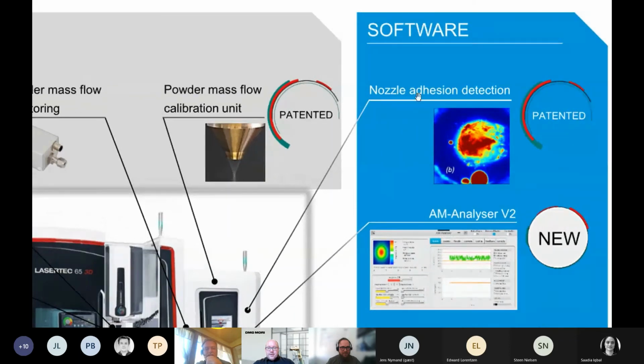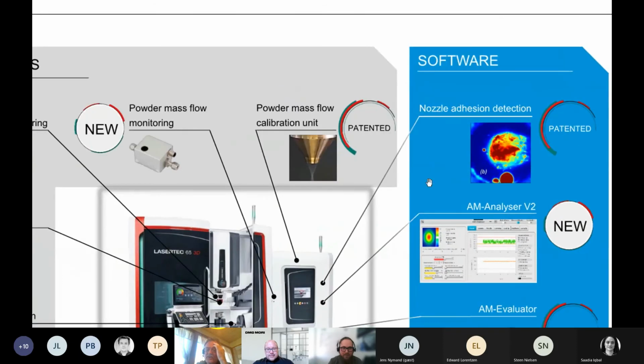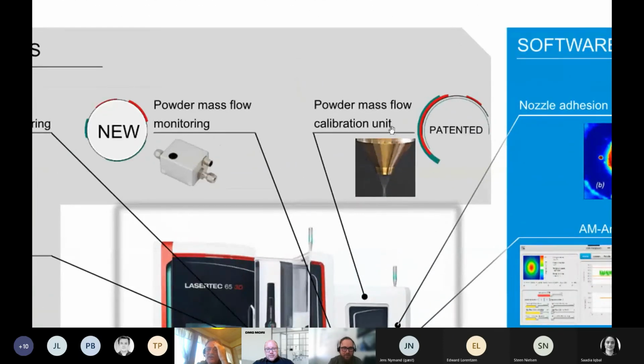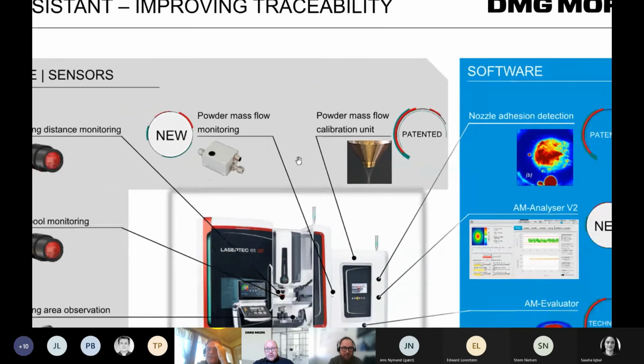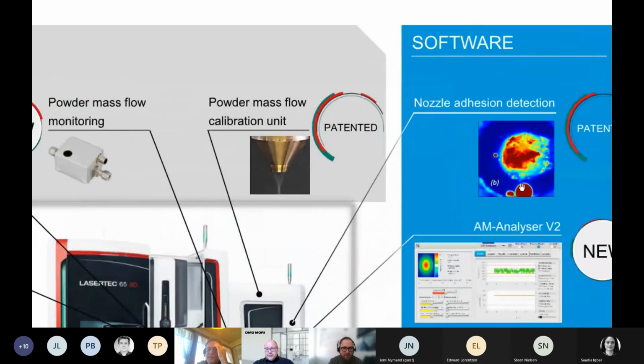We have this nozzle adhesion detection. With a camera looking through the center of the nozzle, we can detect it. Here at the bottom you see these two red balls. That's sticking particles at the end of the nozzle. The shielding glass is way behind the nozzle, not in front of it. Typically, we don't get much trouble with the shielding glass. This is a real attachment to the end of the nozzle, what you can see here.